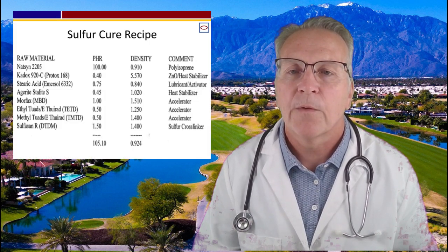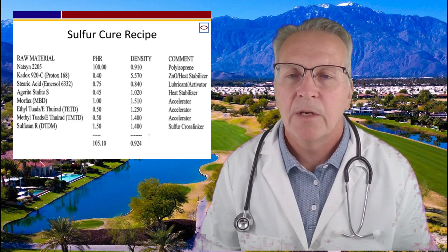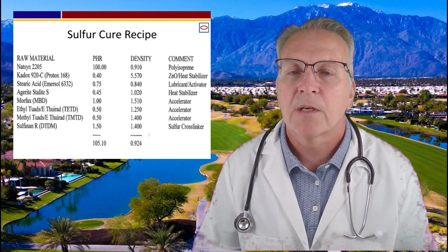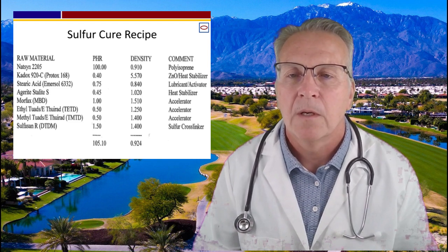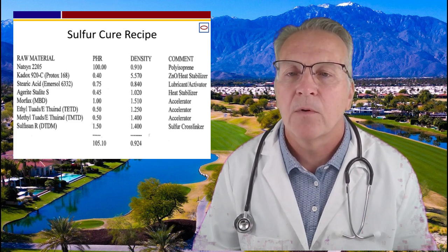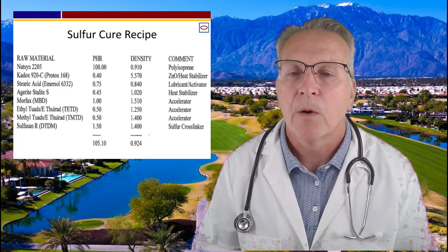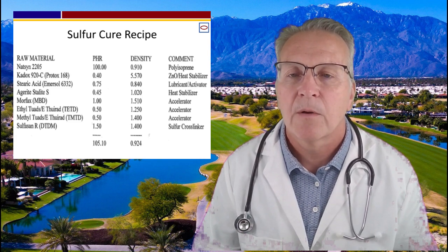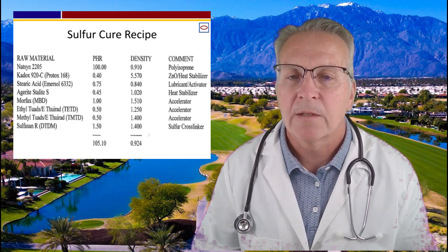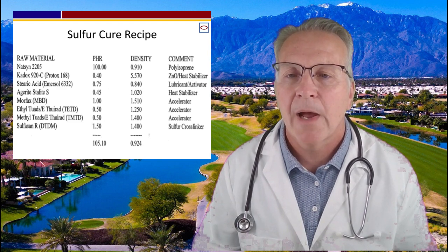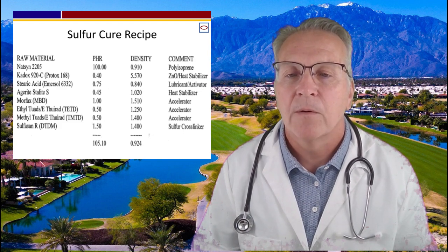I have often said that developing elastomers is more challenging than plastics due to the addition and complexity of the crosslinking system. For sulfur curing, the crosslinking system has activators and accelerators besides the crosslinker sulfur, as shown on your screen. All these ingredients are in low quantities, and to dial in a particular cure level in an elastomer formulation requires precise ingredient measurements, thorough formulation mixing, and consistent processing to complete the crosslinking reactions and give you the same crosslink density month after month and year after year.